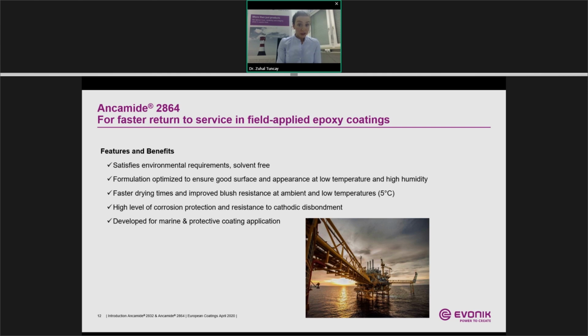2864 is designed for field application, where the environment conditions cannot be controlled. With 2864, very good surface appearance at low temperature and at high humidity can be achieved. At the same time, 2864 provides faster dry time and improved blush resistance, both at ambient and at low temperature. It has a very high level of corrosion protection and resistance to cathodic disbondment.